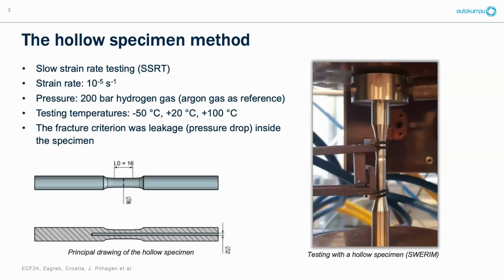So in this project, we have chosen to use this hollow specimen method. It's basically a cylindrical specimen. We drill a hole and fill it with hydrogen gas. And we have utilized slow strain rate testing, but you can also use fatigue testing. The testing parameters were 200 bar hydrogen gas or argon gas as reference, and the testing temperatures were -50, 20, and 100 degrees Celsius.